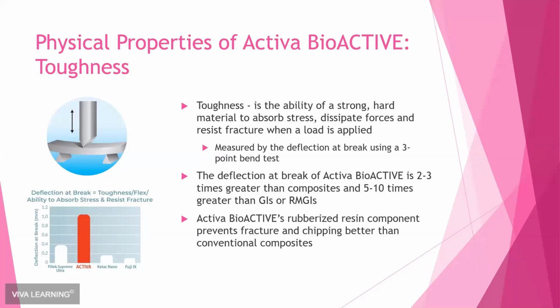And the deflection at break of Activa, which is shown in the graph on the lower left, is showing that it's actually 2 to 3 times greater than traditional composite. Again, we're comparing it to Filtek Supreme Ultra here. And it's 5 to 10 times greater than the glass ionomers or the resin-modified glass ionomers. And this is largely due to the composition of Activa. It's composed partially of a rubberized resin material, and that helps to prevent fracture and chipping better than these other materials that it's being tested against.